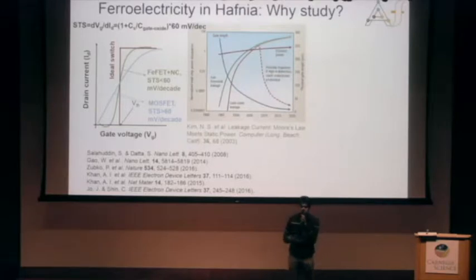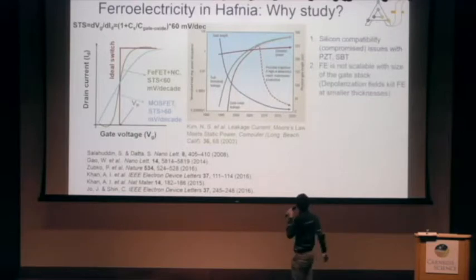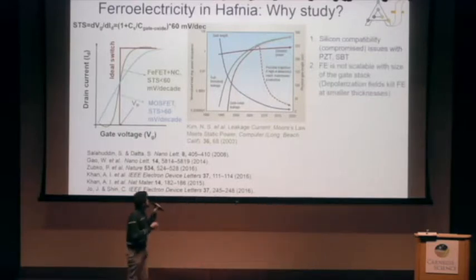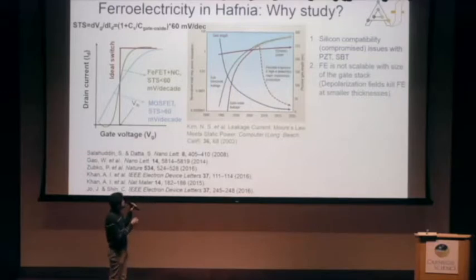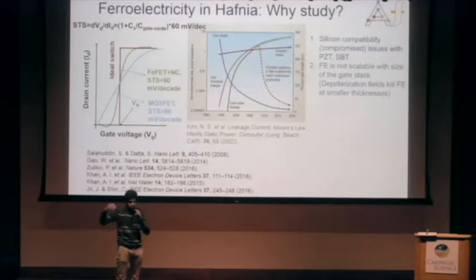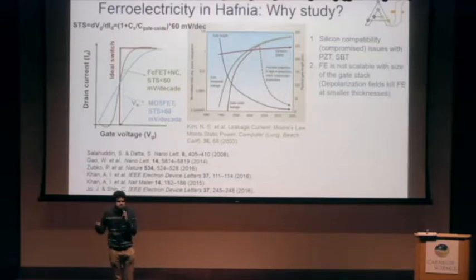Why not use ferroelectrics already in microelectronic ferroelectric FETs? The problem is a well-known silicon compatibility issue with well-known ferroelectrics such as PZT and SBT. And furthermore, as you scale the gate stacks down, these ferroelectric materials lose their ferroelectricity because of depolarization fields.